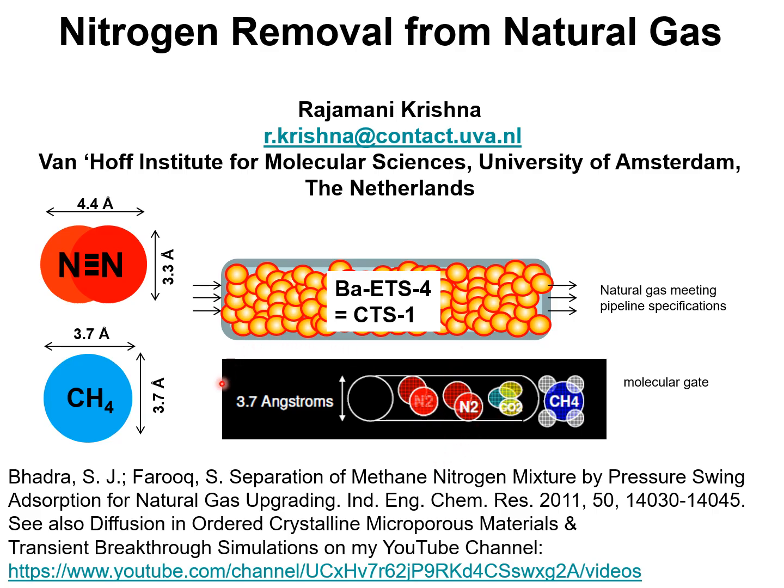And here is a cartoon from the manufacturer which shows the contracted or constricted pores of approximately 3.7 angstrom, which can accommodate nitrogen, because nitrogen is a pencil-like molecule with a smaller cross-sectional dimension of 3.3 angstrom, whereas methane is severely constricted